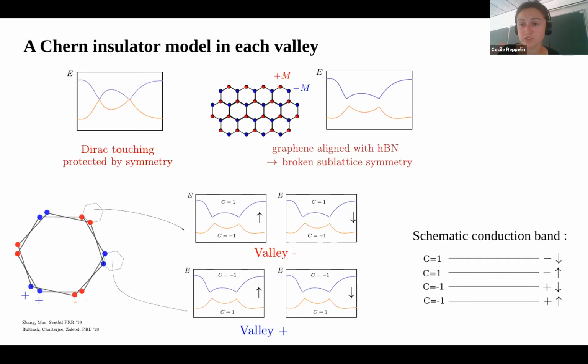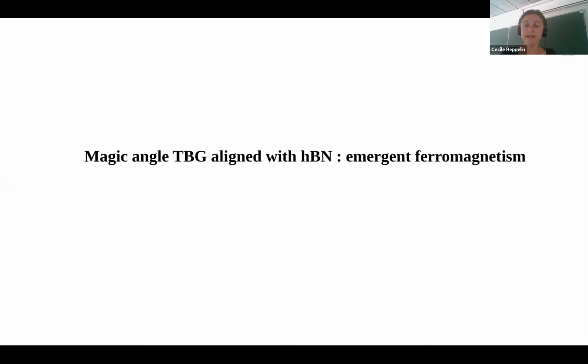So if I focus just on the conduction band, schematically, I have these 4 bands that are almost flat because I'm at magic angle, and that have these different Chern numbers depending on the valley, and additionally I have that spin degeneracy. Okay, so this was the overview of the band structure properties of magic angle twisted bilayer graphene aligned with hexagonal boron nitride. Now I'm adding another element, which is interactions. And this is where we start observing emergent ferromagnetism, as I'll explain now.